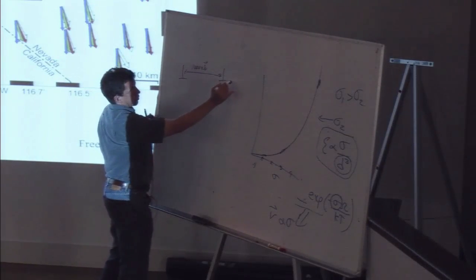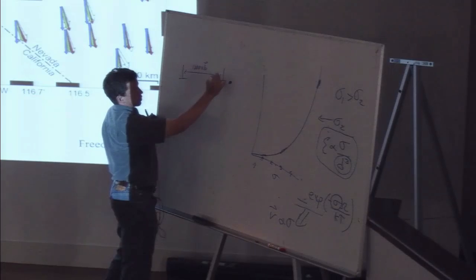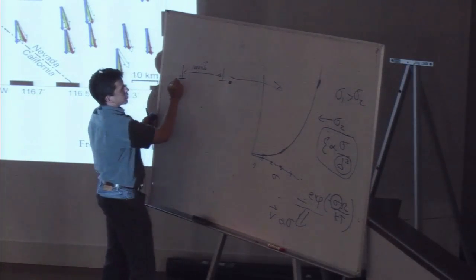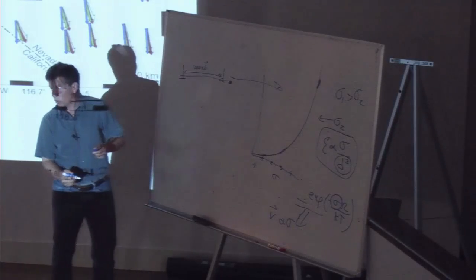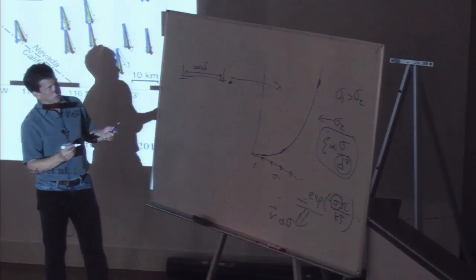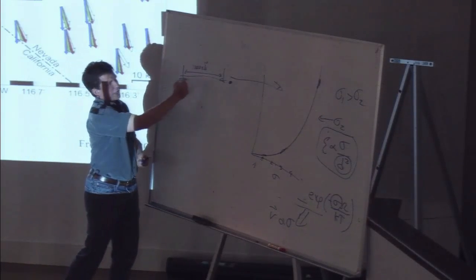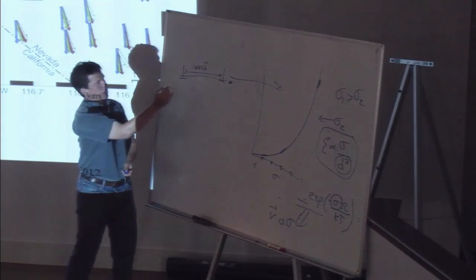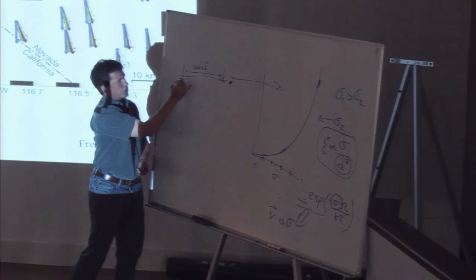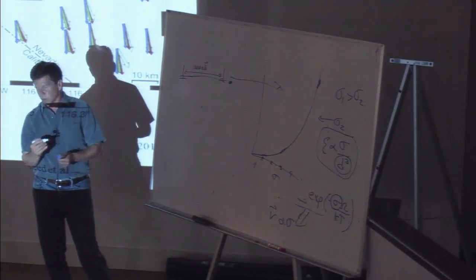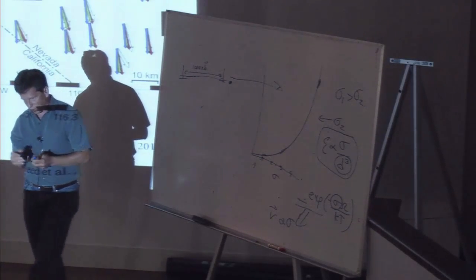And if you get rid of this obstacle by diffusion or if the dislocation climbs, this guy can then zip to here and this guy zips to here. And that process happens almost instantaneously. So in order for glide to be limited, you need to change the conditions such that the glide of the dislocation on each lattice plane is the important step. And so there's two ways of doing that.